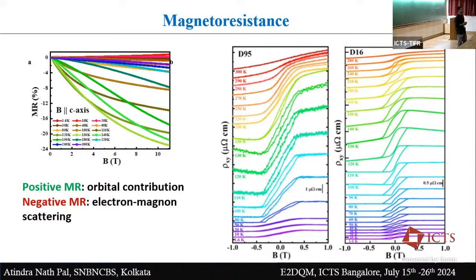But to know that, you have to see the magnetization data also carefully. Magnetization, we checked it. There are no features, and also there is no hysteresis. This was done in a bulk sample, and the magnetization, of course, you have to do in a single crystal, and there the hysteresis is not that prominent. This is only in the thin layer limit what you get.